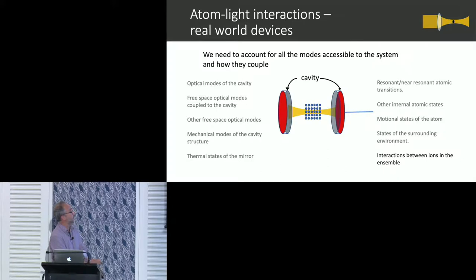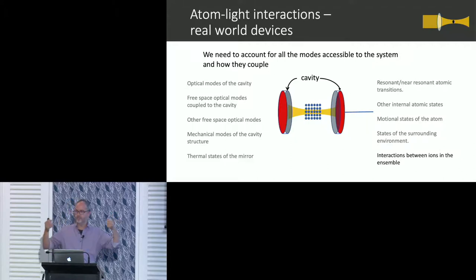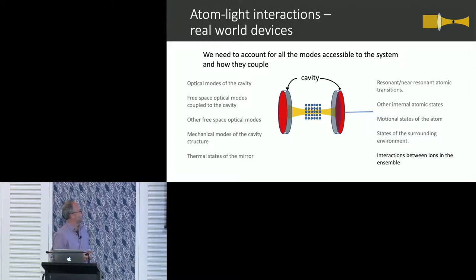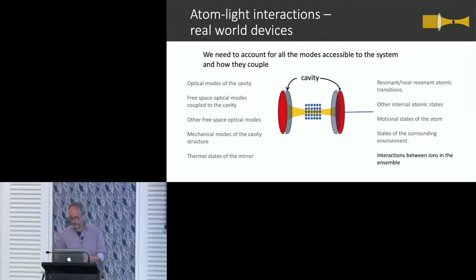As we go to ensembles, we also have to worry about interactions between ions. To get my theoretical memory storage capacity I have to push ions closer together, and at some point they start interacting — this interaction will kill my data storage capacity. Other issues with the host material include phonons coupling into the optical site, charge noise, and magnetic fluctuations. A lot of the work developing these devices is trying to turn all these parasitic interactions off.